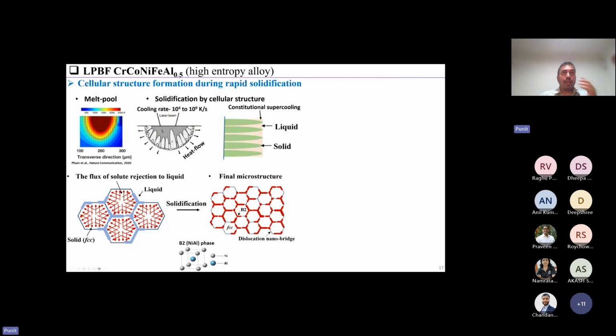And the idea of adding aluminum was that in additive manufacturing you have this huge thermal gradient that I talked about, and you are melting a small amount of material. So because of this combination of high thermal gradient and fast cooling rate, the material usually solidifies in a cellular structure, as I talked about in the introduction. So when these cells are growing, you have constitutional supercooling near these cells, and because of that you have liquid which is rich in solute atoms. And when you add aluminum, these solute rich areas become really rich in aluminum.